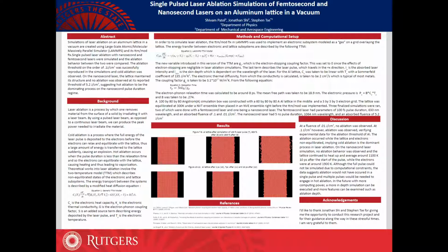However, due to my small simulation box and rather small lattice size, the atoms were able to interact with each other even after being ablated, thus causing heating a long time afterward because the ablated atoms were still inside the electron grid. But if the simulation box was bigger and my lattice was more proportional to an actual thin film of aluminum, I believe this would not have occurred.